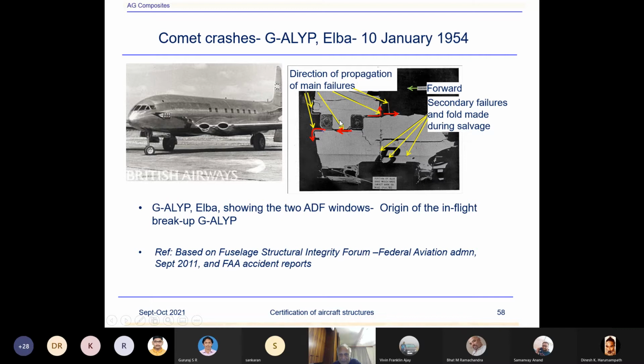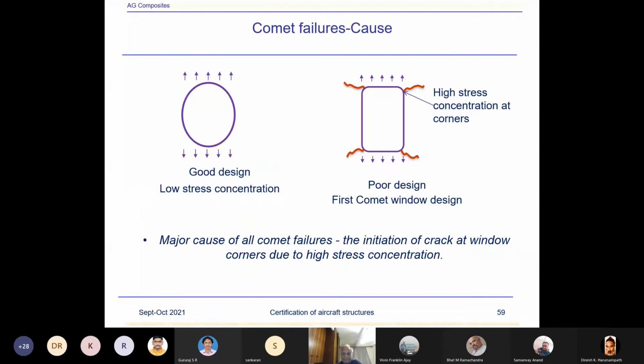But this is what happened. The cracks initiated from the corners in fatigue and led to disastrous failures, which de Havilland didn't realize when they designed this. They, in fact, had proof tested it at twice the design pressure and approved the design. Okay, this just shows the Comet failures: a good design, an elliptic hole, we know that. This is a poor design.